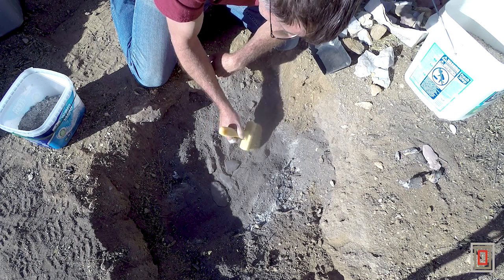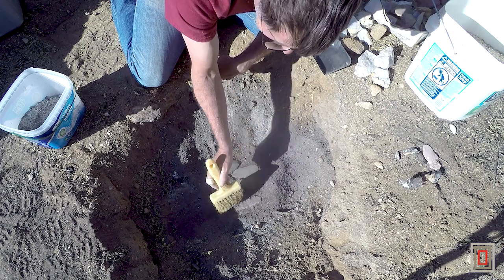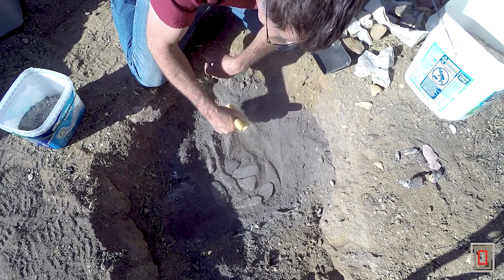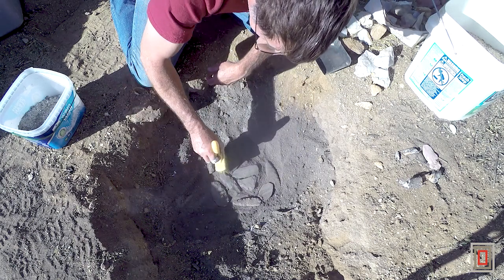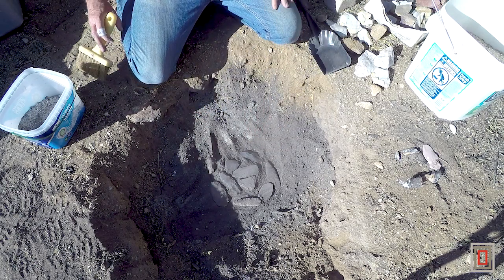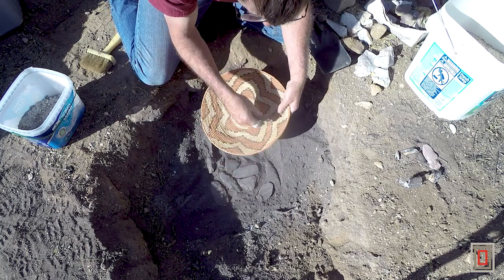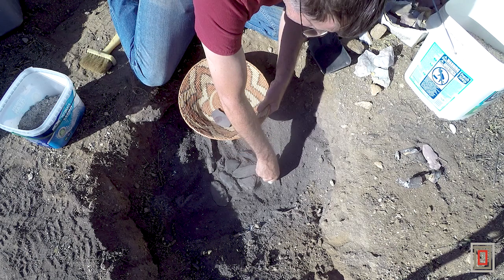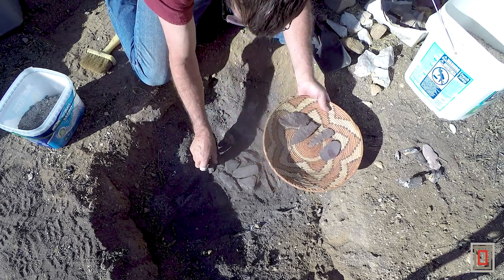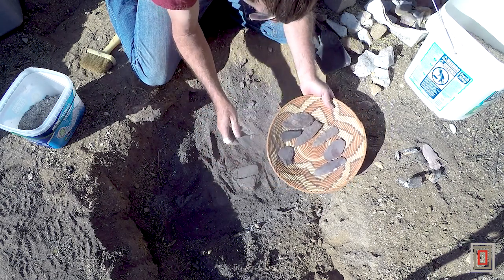There's rock from all over the place in here - a lot of rock from Wyoming, some stuff from Colorado all around. Some pretty nice bifaces. This is sort of that first layer of the thinner stuff. I'll pull them out and keep them in a little basket as I pull them out. This wasn't the hottest heat treating fire I've ever done. I'd rather do several lower-heat firings of the rock than do it too hot and destroy the rock. So we'll see what happens.